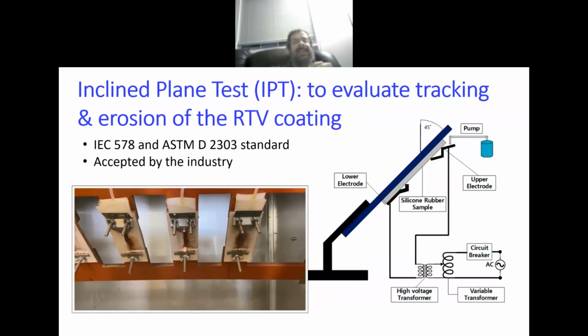Now, how to test this material during the development stage? Since the 60s or even before that, people came up with a test called the inclined plane test. This inclined plane test is used to test both RTV coating and HTV, high temperature vulcanized, the material used for the full insulators. This testing is as per IEC 587 and ASTM D2303. In North America, we use more the ASTM standard. In Europe and the Middle East, we use more the IEC standard.